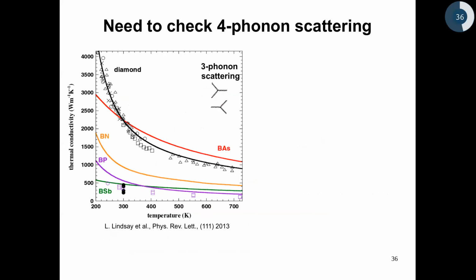In fact, if you go back to the picture I showed you earlier, for the case of diamond, with just 3 phonon scattering calculations, they were able to achieve excellent quantitative agreement with the experimental data. So what this indicates is, in the case of diamond, 3 phonon scattering picture sufficiently describes thermal transport, and any addition of higher order scattering process should not change this curve significantly. But the problem is with boron arsenide, it is not available in nature at that time, so they could not conclude whether the 4 phonon scattering processes are weak enough in boron arsenide or not.